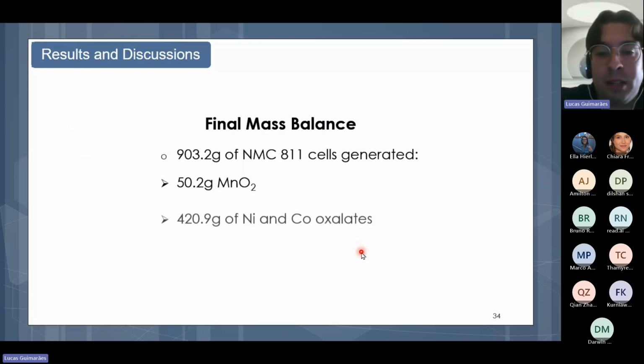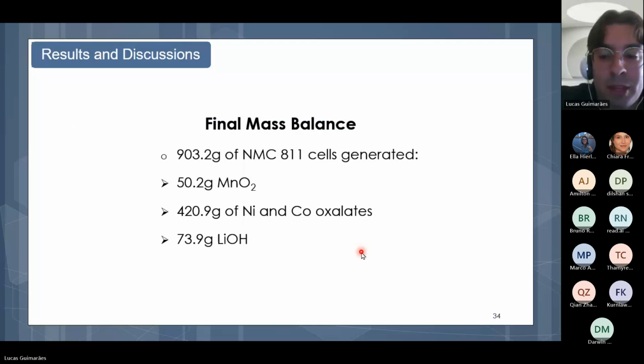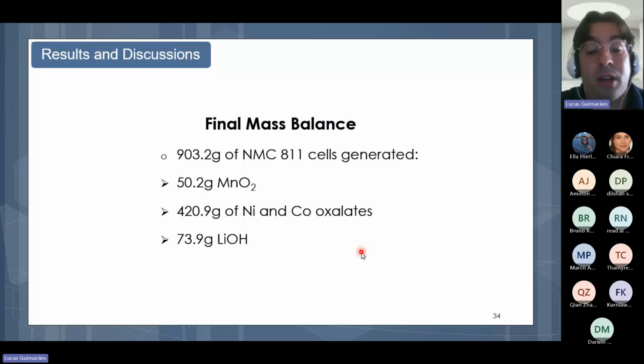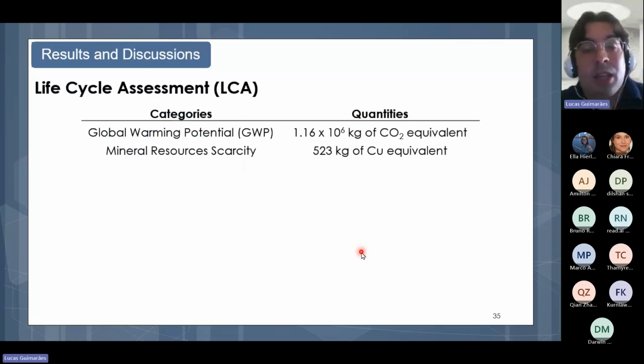So at the end of obtaining the compounds of the metals of interest, a final mass balance was considered. We can presume that in a nutshell, 903 grams of batteries studied generated 50 grams of manganese oxide, 421 grams of nickel and cobalt oxalates, and 73.9 grams of lithium hydroxide.